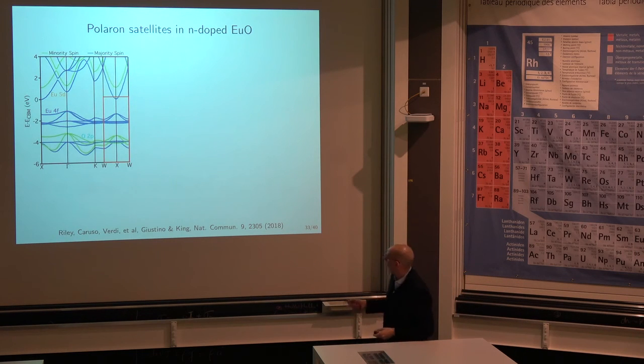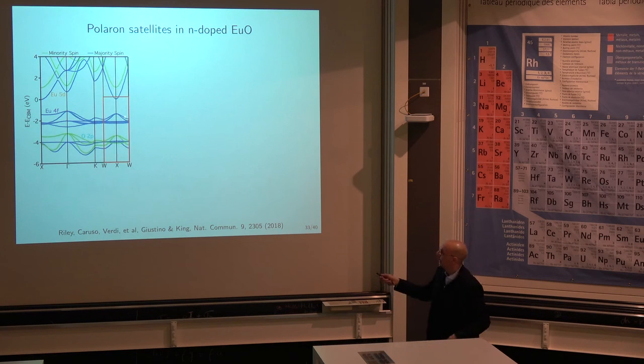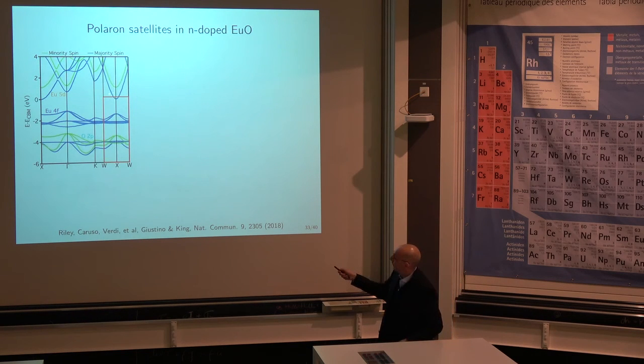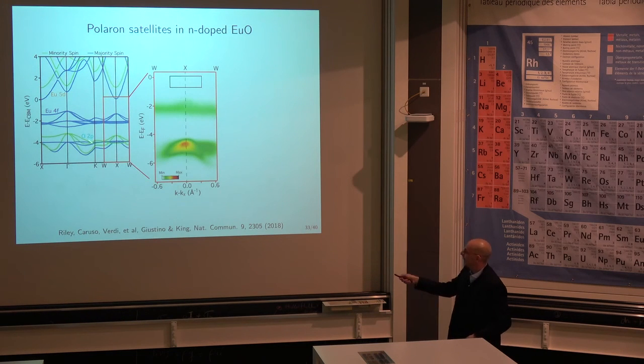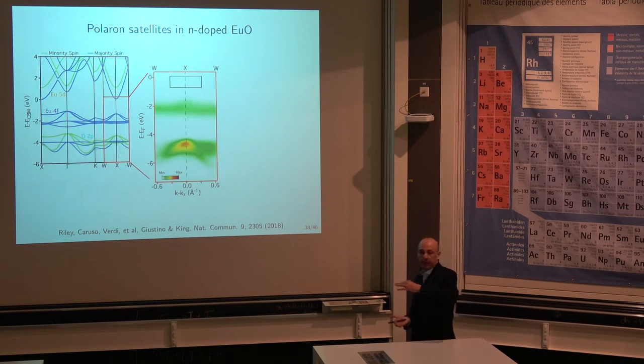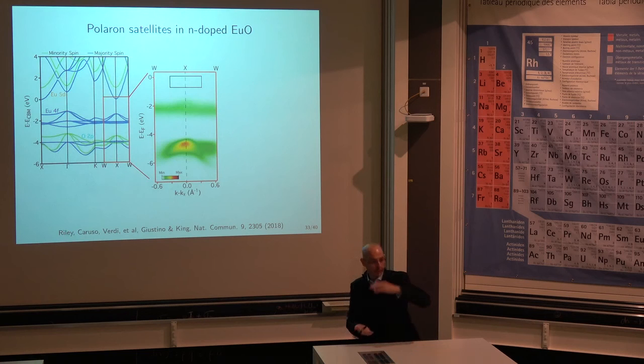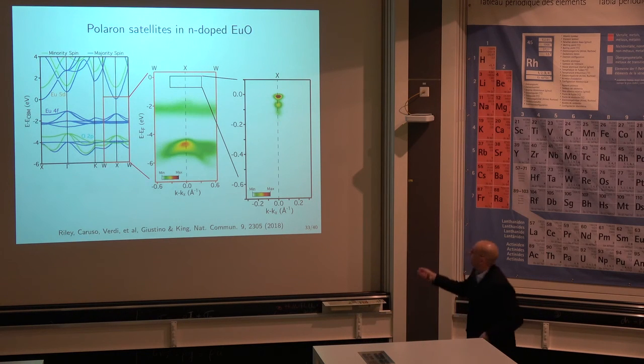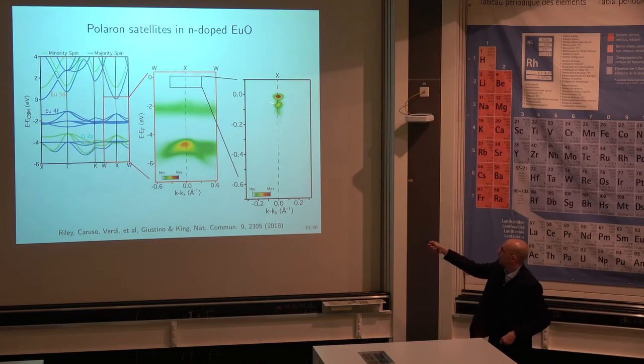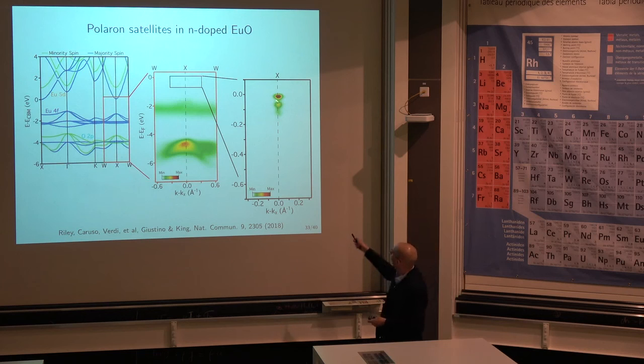So here, what the group of Phil King did is to essentially dope it with gadolinium. That means that you should be placing some electrons in the conduction band bottom. Then they did the ARPES spectra, so you recognize the oxygen 2p band here, the europium 4f here, and then we would expect to see something here, right? And you don't see anything. But this is quite typical in ARPES. When the signals are small, you don't see much, but you can zoom in. If you zoom in, you find something here that corresponds to the conduction band bottom, and you find this object. So again, we find a conduction band bottom, plus a couple of polaron replicas.